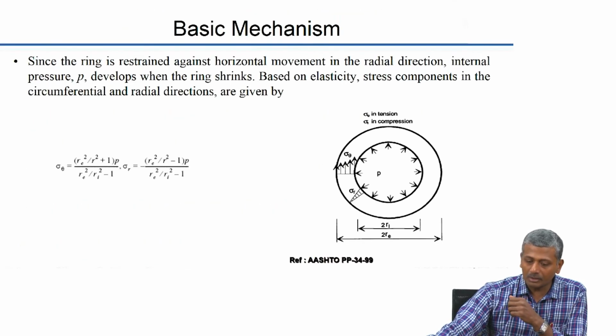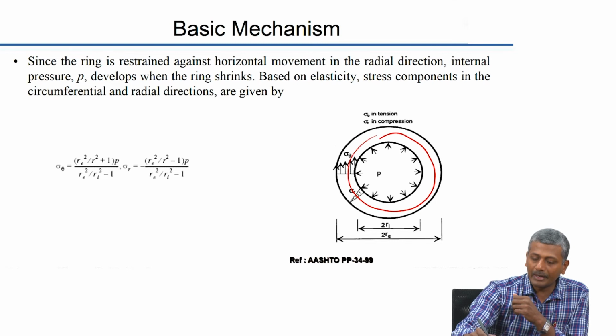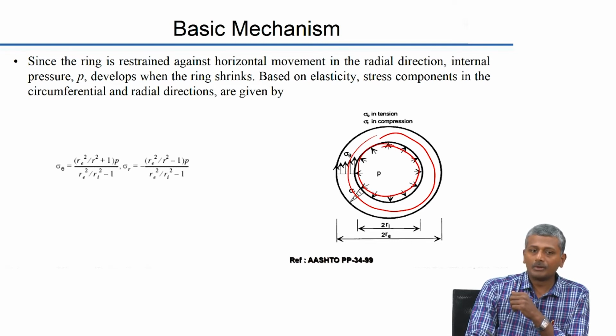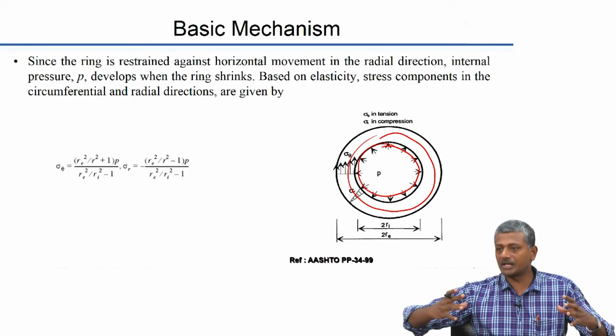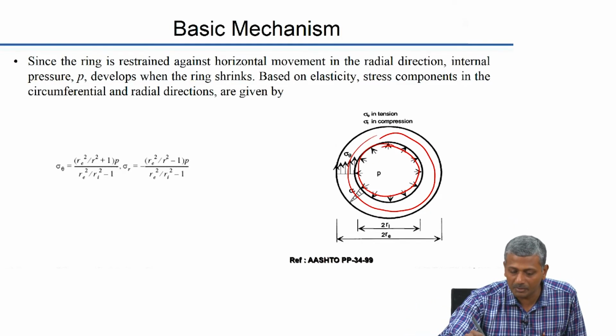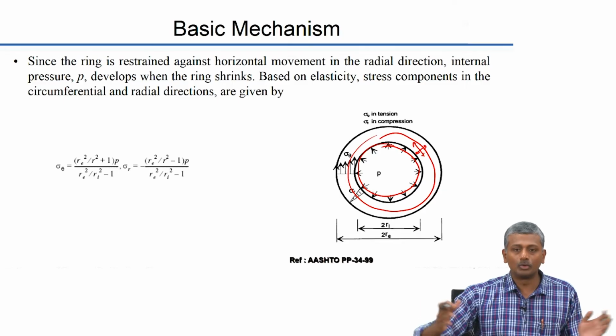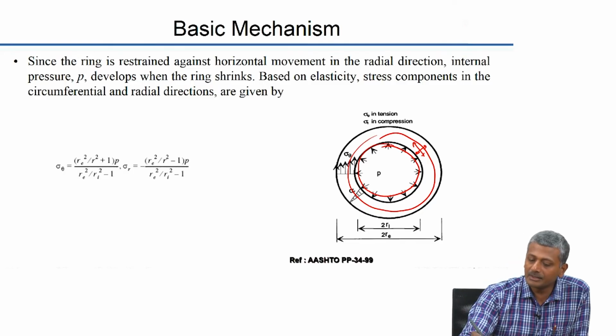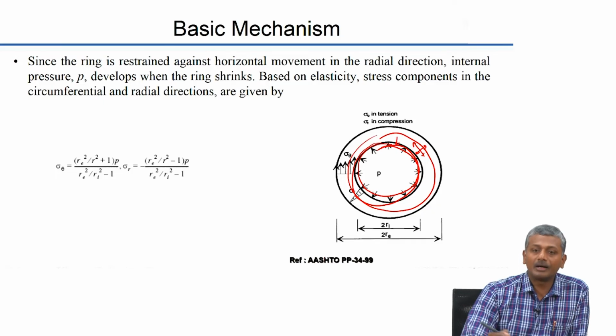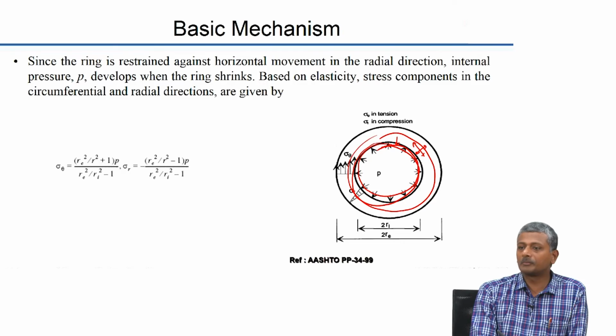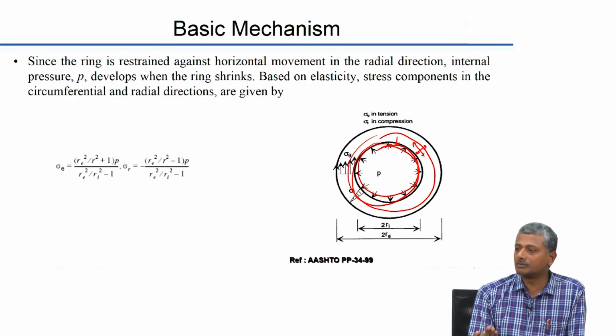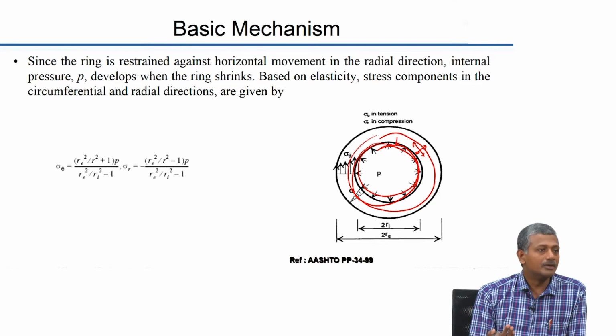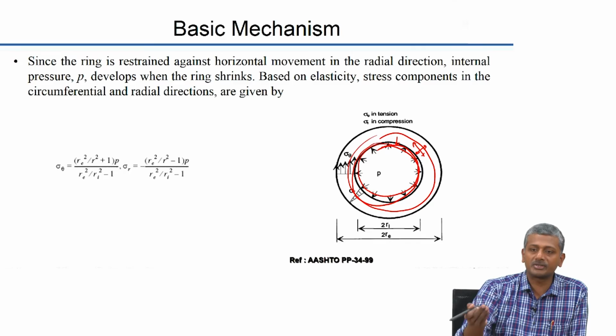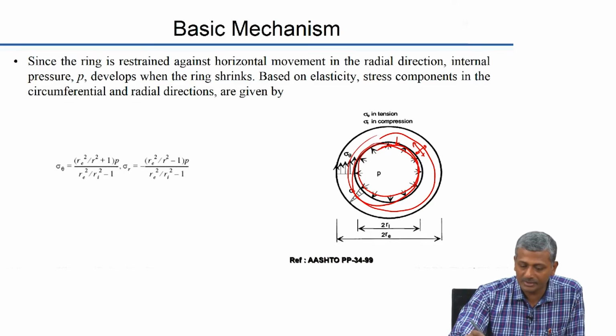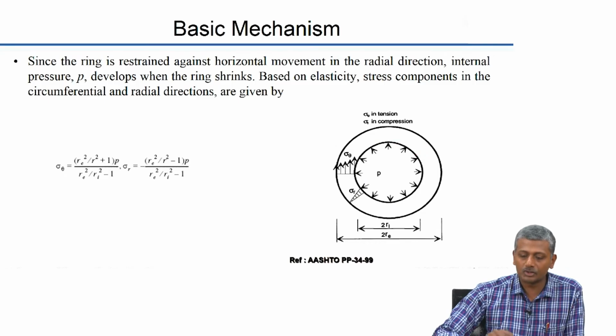So, here what happens is you have a concrete ring, this is the concrete ring, and there is a steel ring inside of the concrete ring. So, this concrete ring, because of the nature of concrete, will start shrinking, because shrinkage will produce volumetric deformations in both directions. As it is shrinking, the resultant stress, because of the restraint offered by this steel ring, will be translated into a development of strain in the steel. Now, steel at that level of stress will be in its elastic state, nothing will happen to the steel. So, once you measure the strain in the steel, you can automatically measure the stress in the concrete, which is causing the cracking. So, that is what this restrained ring test is. I am not going into the details of this, I will show you the results in more detail.